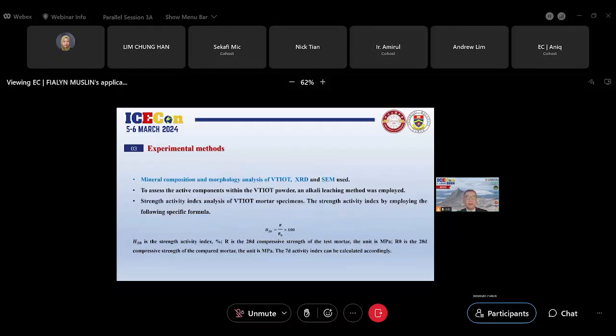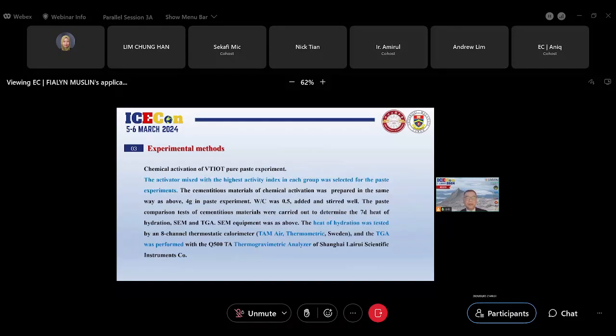Mineral composition and morphology analysis of VTIOT used XRD and SEM, and to assess the active component within the VTIOT powder, the alkaline leaching method was employed. The strength activity index was calculated by the following specific formula. The activator matched with the highest activity index in each group was selected for the paste experiment, and heat of hydration used TAM Air, and TG used a thermogravimetric analyzer.